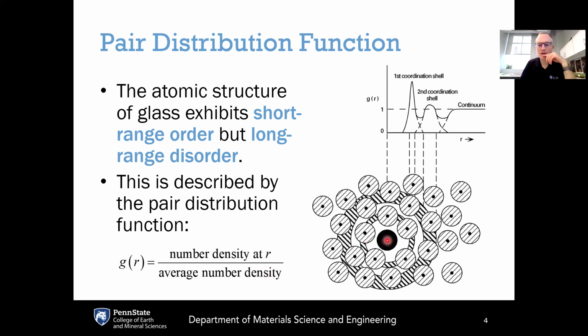So if we start here at r equals 0, the pair distribution function is 0 because the probability of finding some other atom at the exact same location as your central atom is 0, right? We know that Pauli's exclusion principle from quantum mechanics forbids two atoms from being at exactly the same position. And as a result, this pair distribution function is going to be 0 because there's a 0 probability of finding another atom exactly overlapping with your central atom.